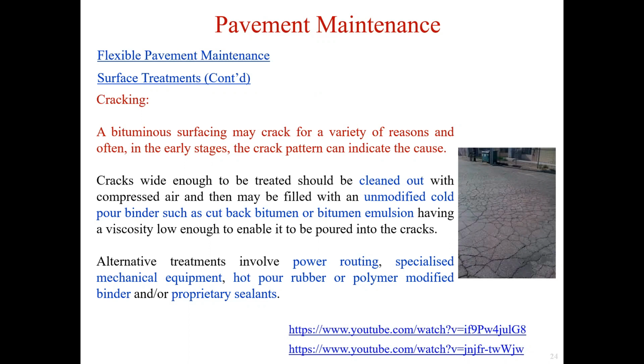Evidence of alligator cracking is an indication of pavement fatigue failure, and crack sealing is not appropriate for these areas. There are some alternative treatments such as power routing, specialized mechanical equipment, hot pour rubber, or polymer modified binder, and or proprietary sealants.